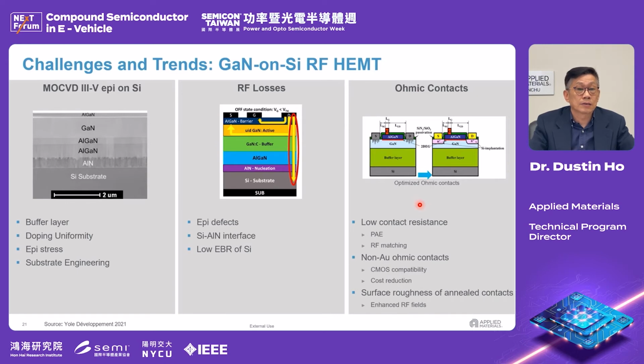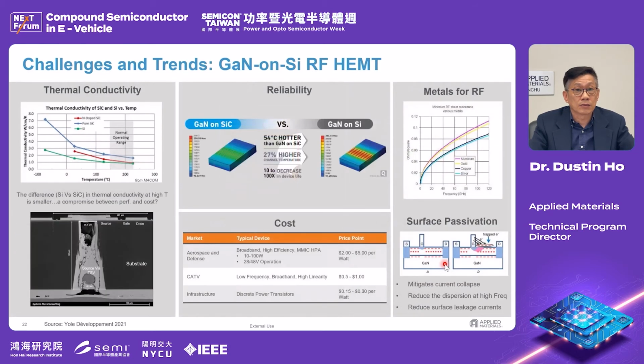And for the ohmic contact, everybody wants to reduce the contact resistance to improve the efficiency, and also needs a non-gold ohmic contact process. And in theory, maybe copper is very good for this also. Because it's for RF, the surface roughness will be critical for the RF application. And this will emphasize the etch and the ALE importance. And with the thermal conductivity, GaN on silicon is only good for low power because of the heat dissipation issue, right?